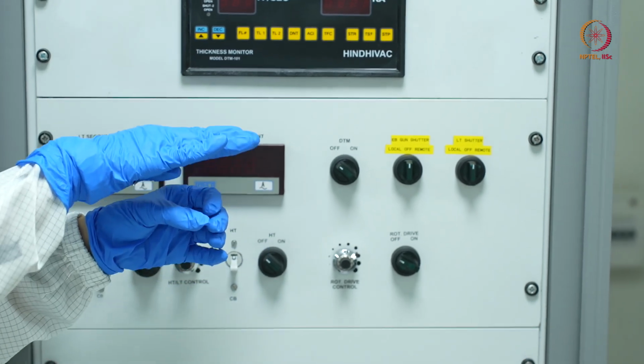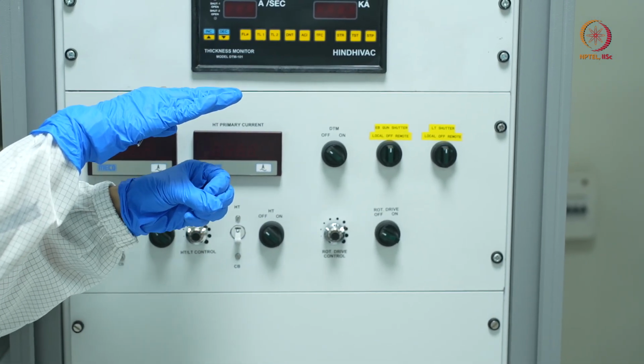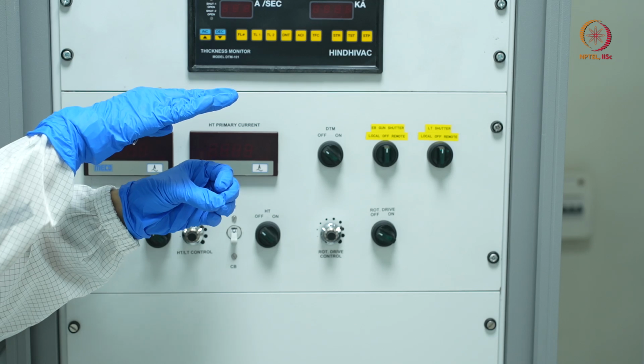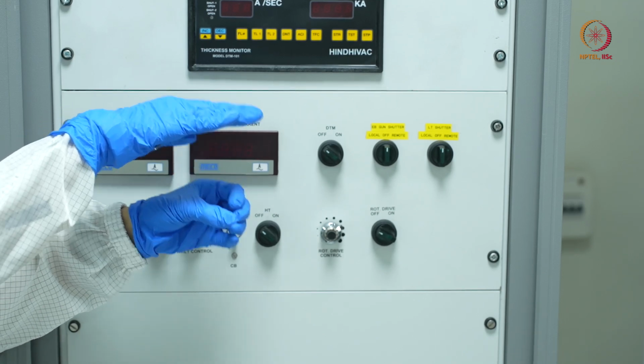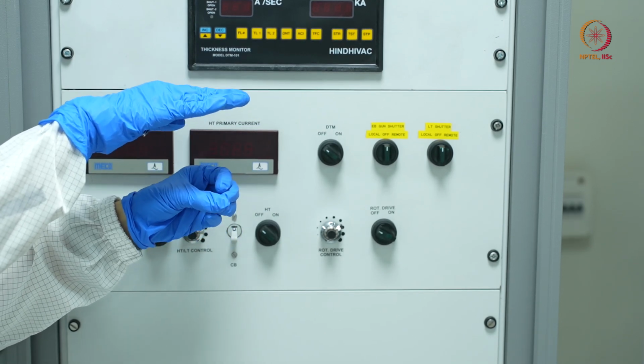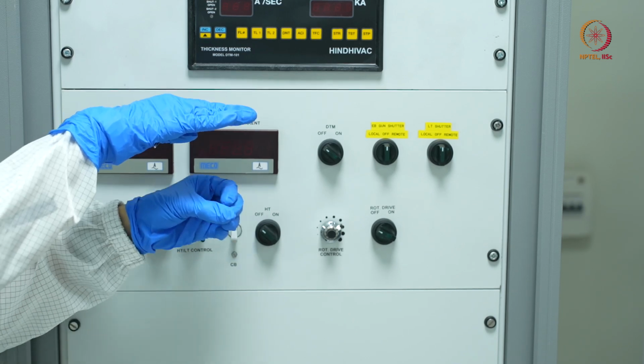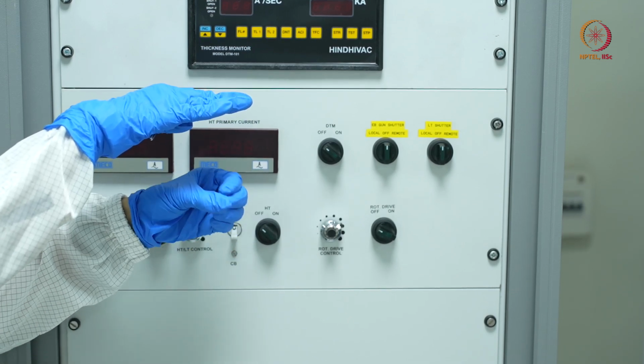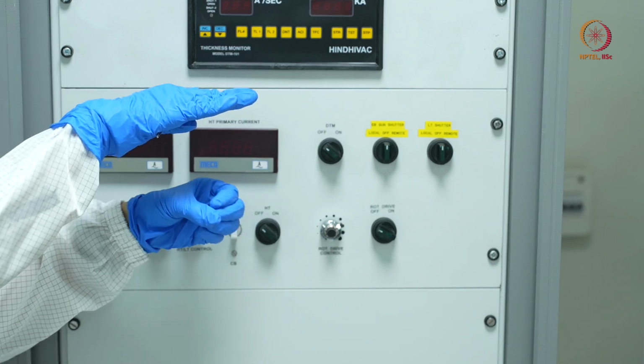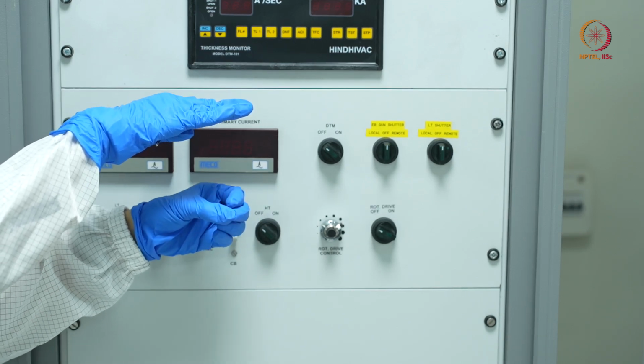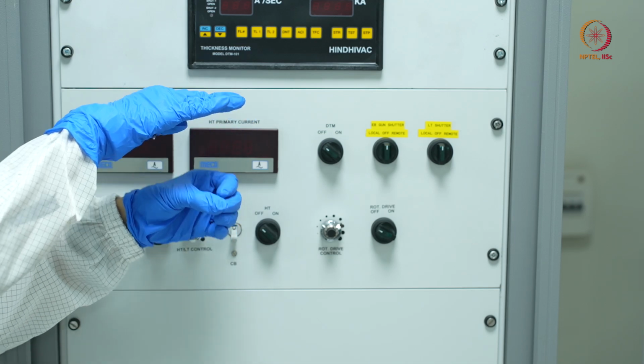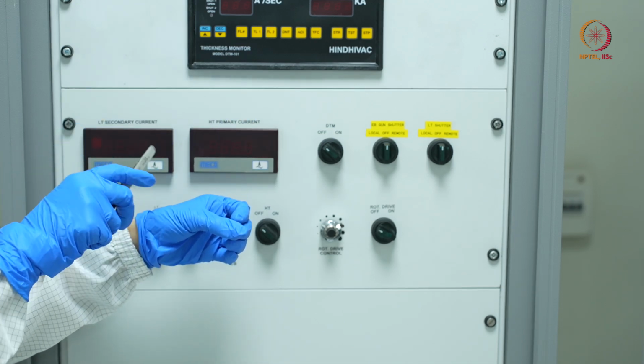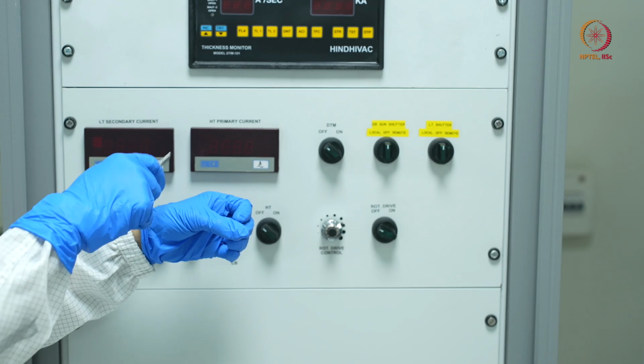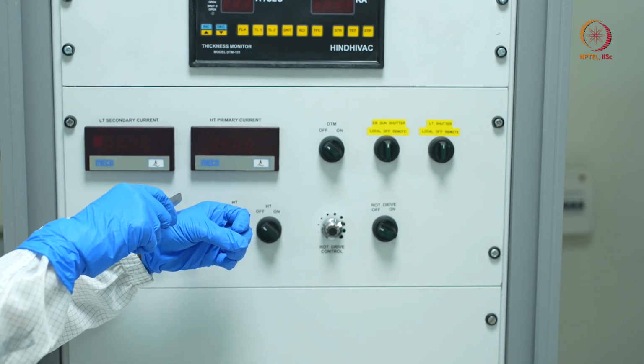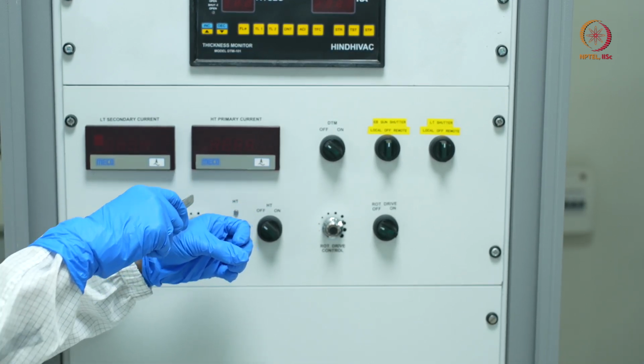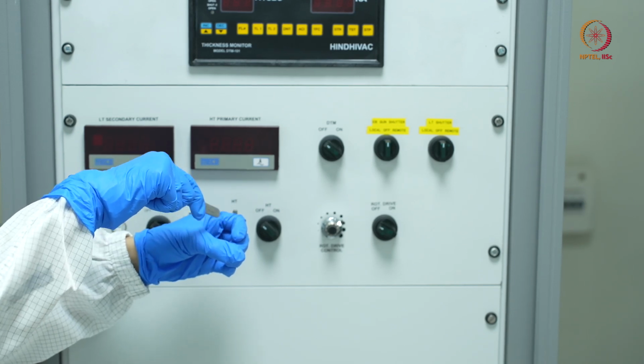You will need to do preheating of the basket so that whatever material is inside the basket melts. For example, in this class we'll be depositing aluminium, so I'll be keeping some aluminium pellets inside my basket, so that the aluminium pellets melt before I start the deposition. Once I supply current, the basket will start getting heated up.